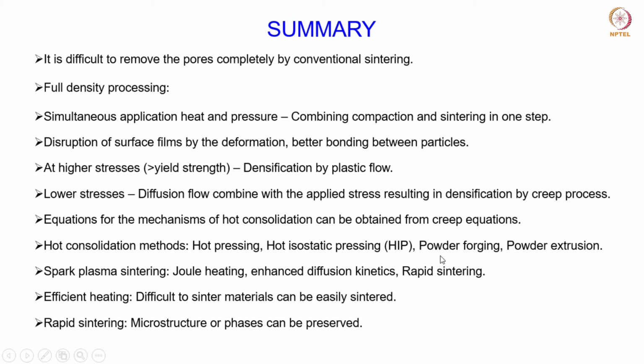And then we talked about other two hot consolidation processes, and these were powder forging and powder extrusion. So this is basically deforming the powder inside dies to achieve the densification during this hot deformation. And then we talked about a process called spark plasma sintering, which is quite different from all other sintering processes that we discussed before it, because in this case the heating mechanism is completely different.